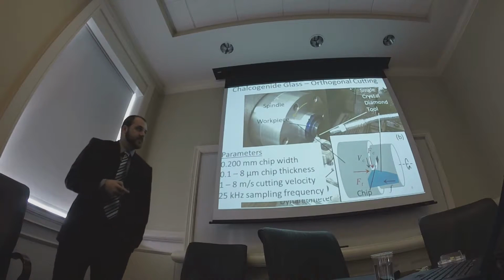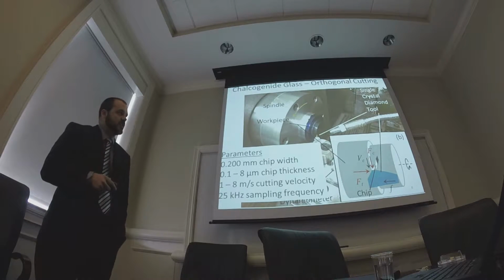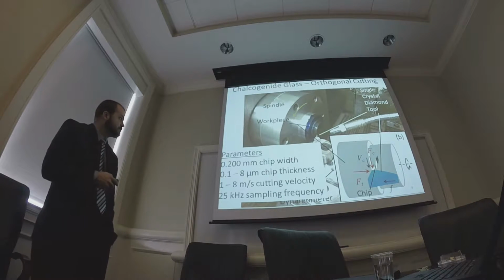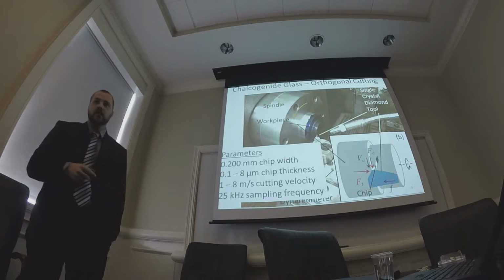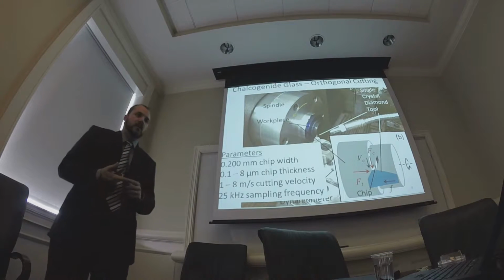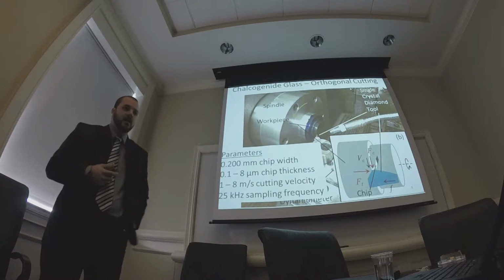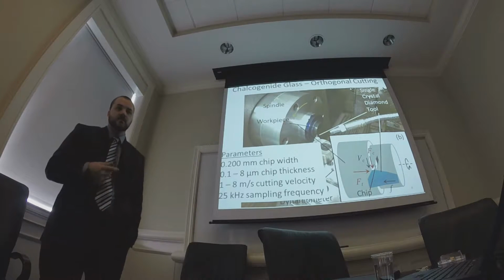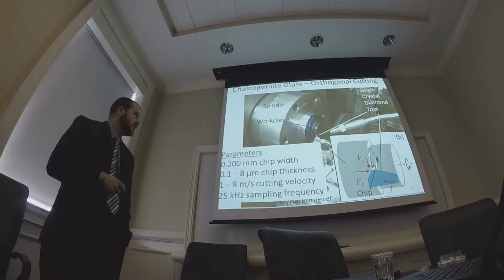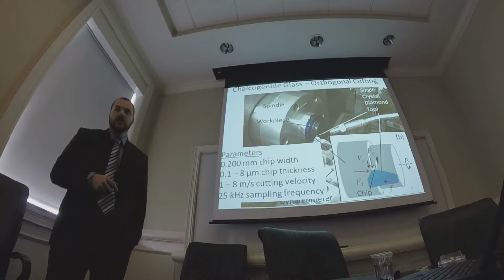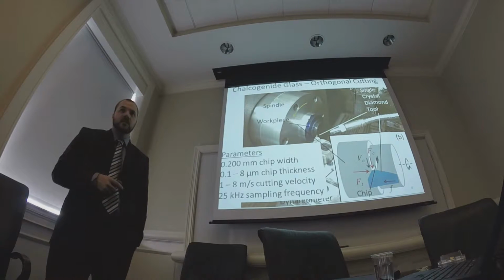So this is sort of the simplified geometry I was talking about. With a zero rake configuration, we got a cutting force and a thrust force, and I said 200 micron chip width. We did chip thicknesses from 100 nanometers to 8 microns, and we tested some speeds from 1 to 8 meters per second. All of our data sampling was done at 5 times the natural frequency of the dynamometer.